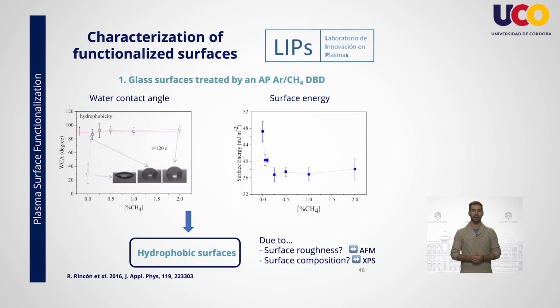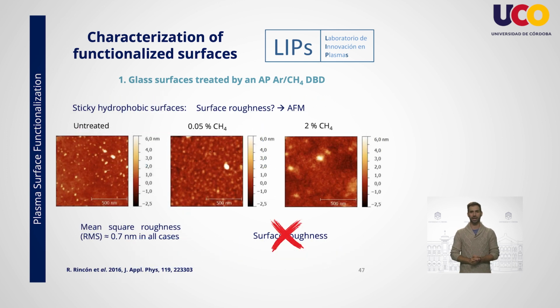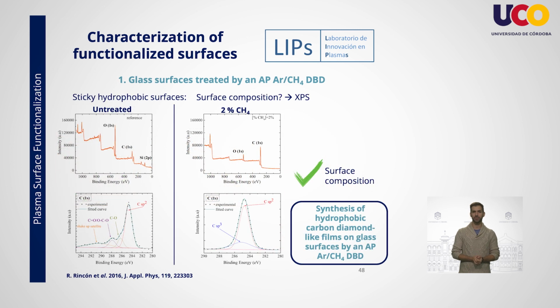According to the bibliography, the hydrophobicity could be due to changes generated either in the surface roughness or composition. The surface morphology was therefore analyzed by atomic force microscopy. Here we can see two-dimensional AFM images obtained before and after treatments. From these maps, the mean square roughness can be calculated, obtaining a similar value for all the different cases. This indicates that the surface topography is not a contributing factor. So, the next step, therefore, was to check for compositional changes after plasma treatment, for which XPS was used.